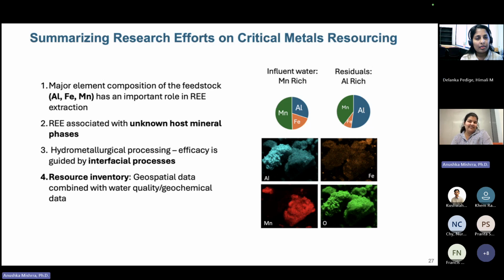Yeah, this is a very good question, because this is why we are doing this, because there is a big difference in the concentration, like you mentioned. There are high metal loadings for iron, aluminum, manganese, and low REs. One of the techniques, the way I have been able to show you data over here, is through ICP-MS, which is basically mass spectrometry. So we're getting numbers out of these, and we are also looking at what interferences iron or aluminum or manganese have. Luckily for the rare earth elements, the interferences, like for the iron, would be at a higher atomic weight ratio, and the interferences that we have don't really reflect much on the REEs.